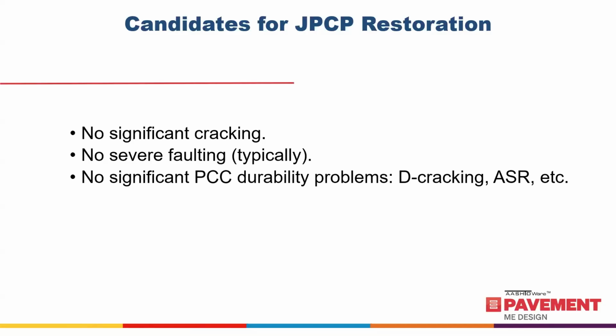No significant durability problems. In other words, no concrete cancer, D-cracking, alkali silica reaction, some of the other nasty things that can happen to concrete. Once it starts, it's going to continue. And really, at that point, if you want to retain the concrete pavement in some manner in the structure, covering it up is probably the best thing you can do because that will slow down or inhibit the infiltration of chlorides and other nasty things that get into it through water or precipitation. And you can slow down the deterioration in the concrete pavement and get more life out of it.